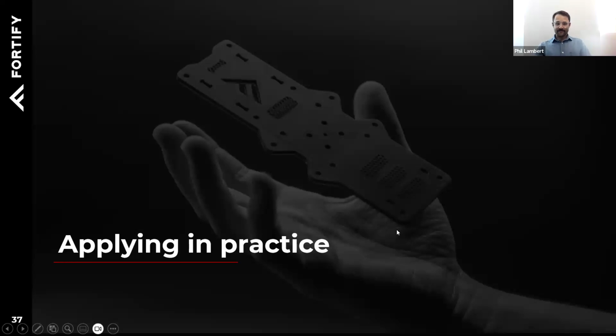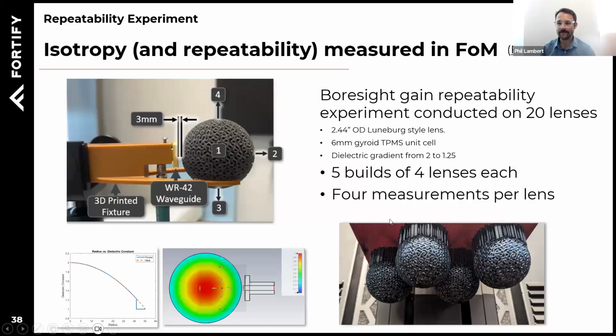Okay, so applying this in practice, we're going to quickly look at a repeatability experiment that Fortify ran using a tennis ball sized Luneburg lens, 6 millimeter gyroids with a dielectric gradient of about 2 to 1.25 simulated. And then we ran an experiment where we took this lens and put it into a fixture in front of a WR42 waveguide. And then we turned it into 4 different directions. So we measured it from 4 different orientations of the device and effectively 4 different orientations of that unit cell to look at repeatability in our manufacturing process, but also in our design.